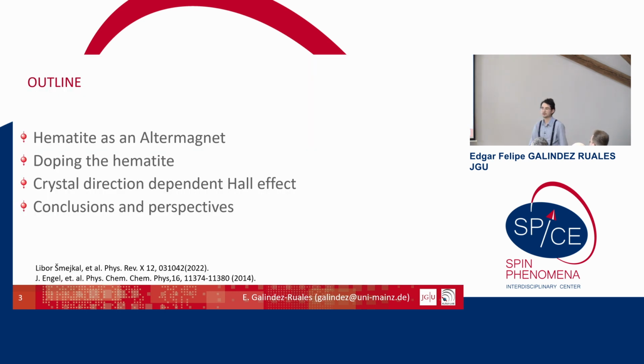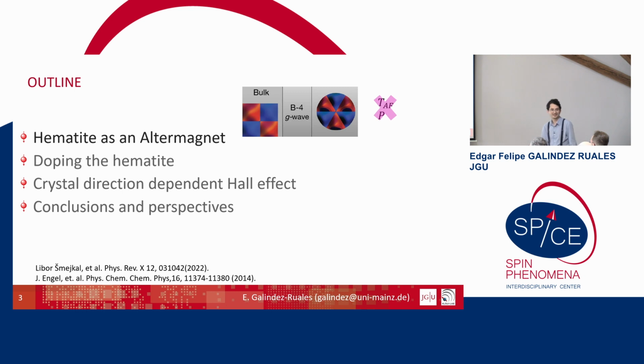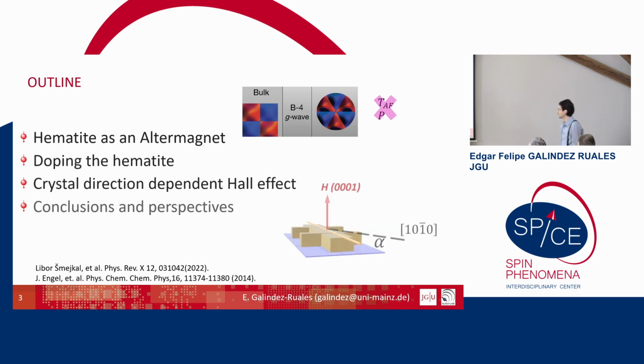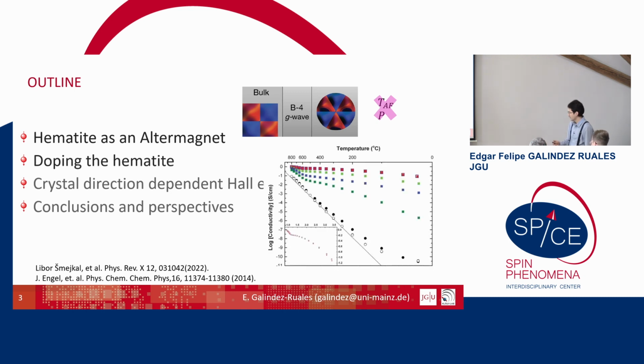So in my talk today, I will start with hematite as an altermagnet. It was shocking for us that hematite, a well-known antiferromagnet, is not an antiferromagnet, it's an altermagnet. That was kind of collapsing a lot of theory. Then I will talk a little bit about how we make this hematite a little bit conductive, because we need to measure transport properties, and probably you know, hematite is known to be an insulating material. So we have to dope it. The conductivity of hematite is super low, and when we start increasing the doping, we can reach measurable levels.